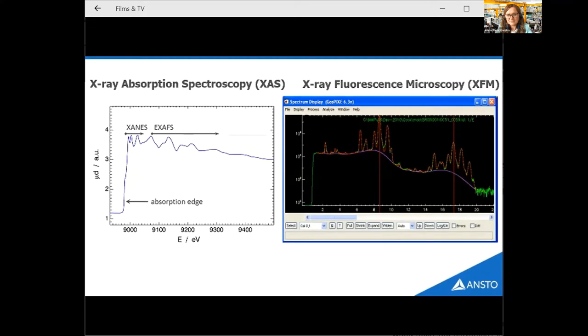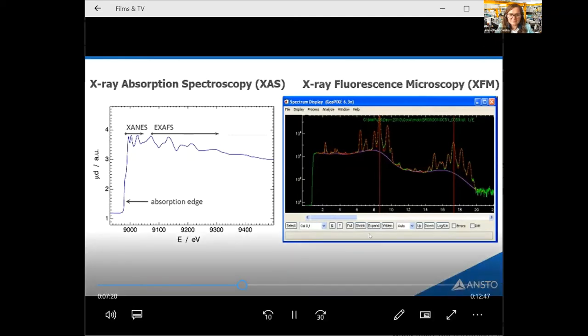And each one of these peaks is a different energy, so fluorescence from a different element. We can fit this and calculate which elements are there and quantify them. And because fluorescence is proportional to absorption, the XFM beamline can also measure the oxidation state and the speciation of elements and map these too.